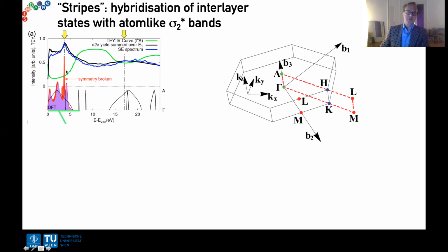So there, the incoming electrons can penetrate into the surface, whereas in the region of the band gap here between 5 and 15 eV approximately, the wave function cannot penetrate the surface, and you see accordingly a very strong rise in the electron reflectivity.